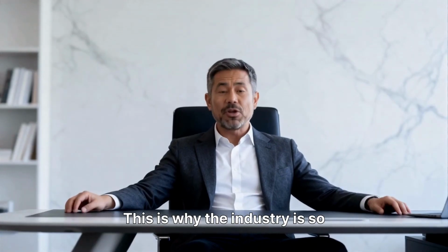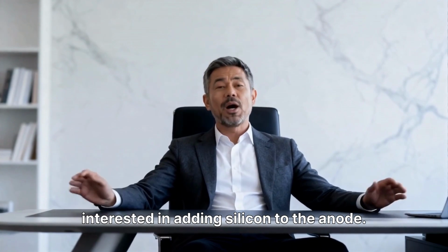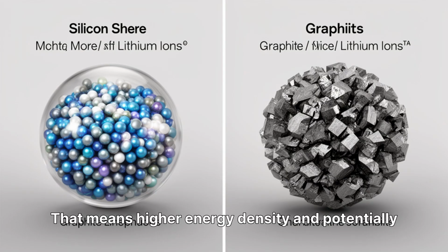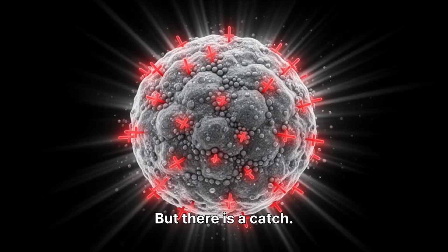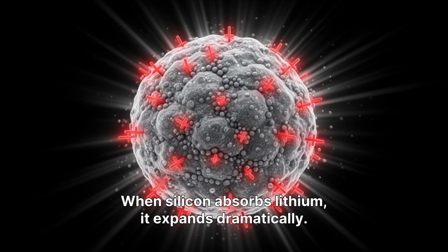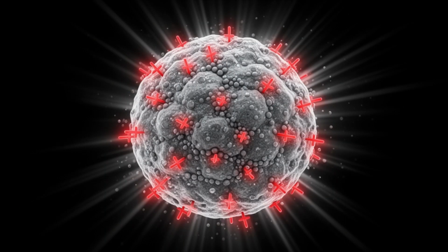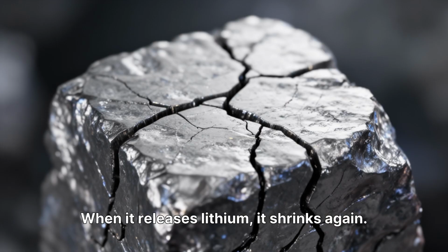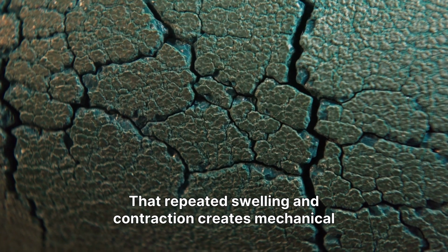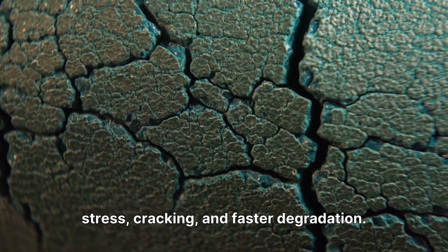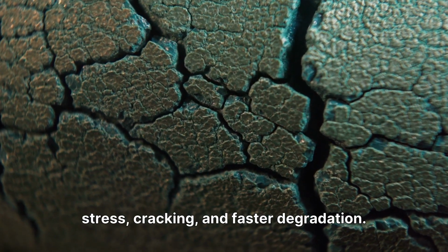This is why the industry is so interested in adding silicon to the anode. Silicon can theoretically store much more lithium than graphite. That means higher energy density and potentially more range. But there is a catch. When silicon absorbs lithium, it expands dramatically. When it releases lithium, it shrinks again. That repeated swelling and contraction creates mechanical stress, cracking, and faster degradation.